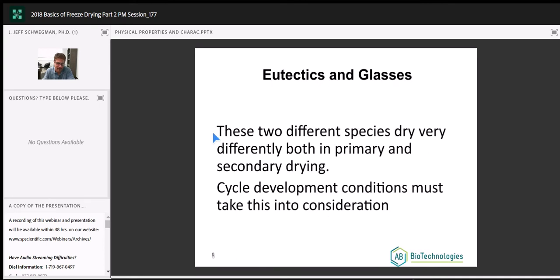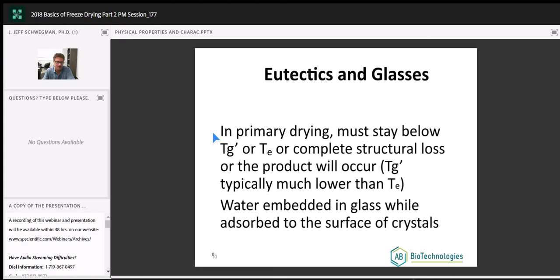Again, these two species dry very differently, in secondary drying and primary drying. So how we develop a cycle, we have to know what we have. Is it crystalline? Is it amorphous? Is it a mixed system? And again, like we mentioned before, in primary drying, we need to stay below that Tg prime, glass transition temperature, or eutectic melting temperature, or we do run the risk of complete structural loss of the product during primary drying, collapse.